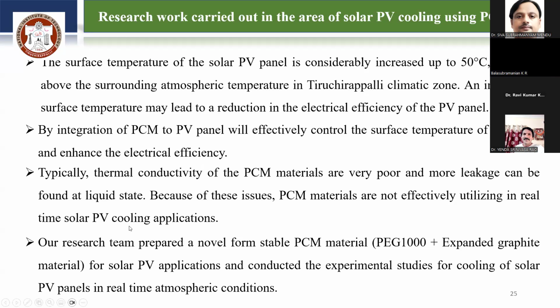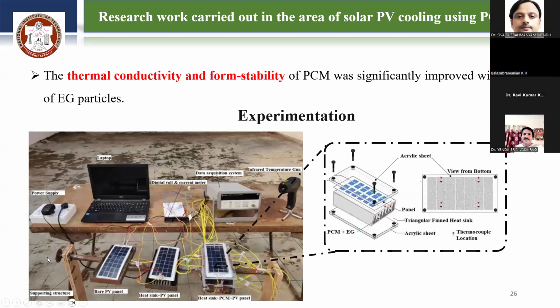So our research team has prepared a novel form-stable PCM material. Polyethylene glycol 1000 is used, and we added expanded graphite material. The experiment was conducted in real-time atmospheric conditions. Here you can see the experimental setup, where there are three types of panels. One is the bare PV panel, where there is no external cooling, only normal air cooling. The second one is the PV panel attached with the heat sink. The third one is the PV panel with the heat sink and the PCM.